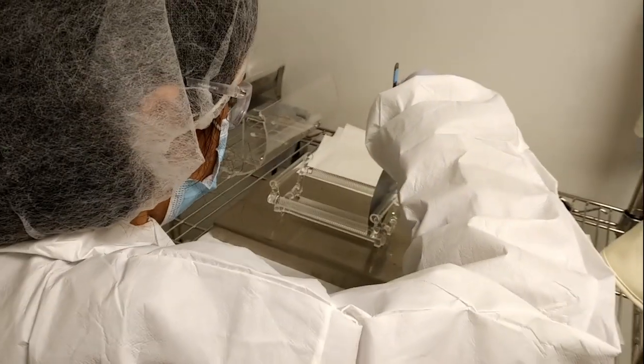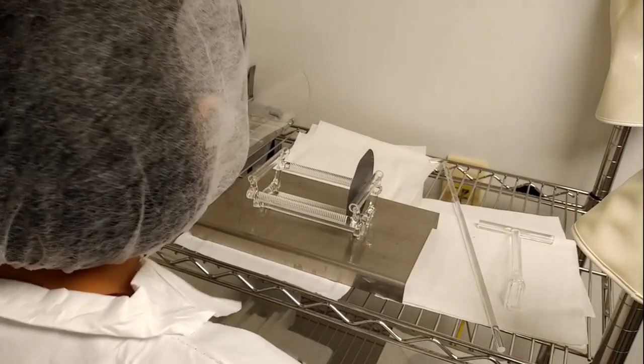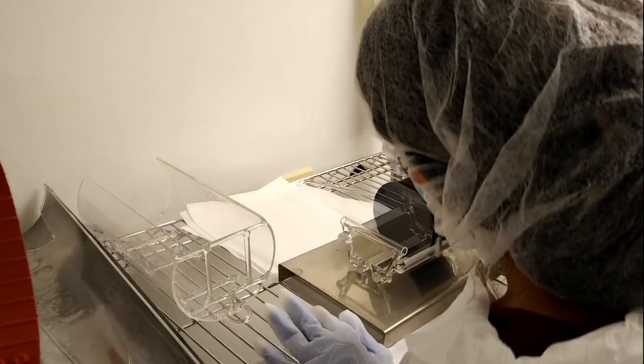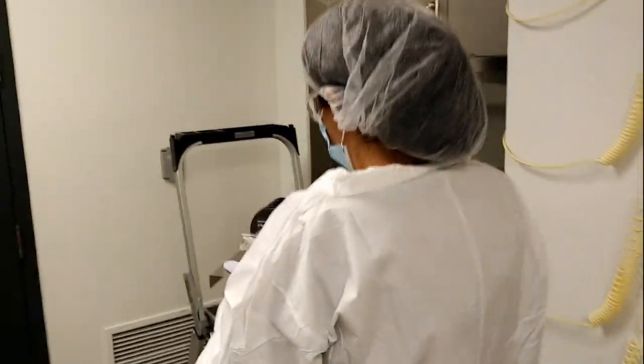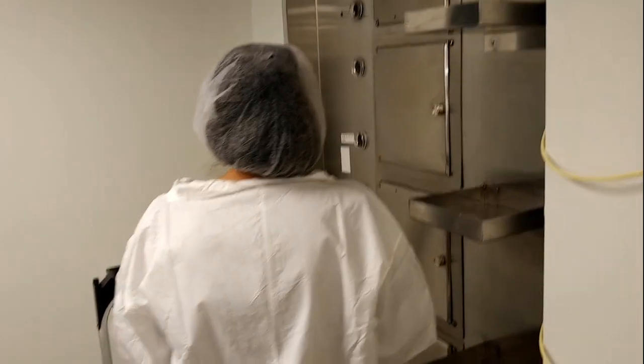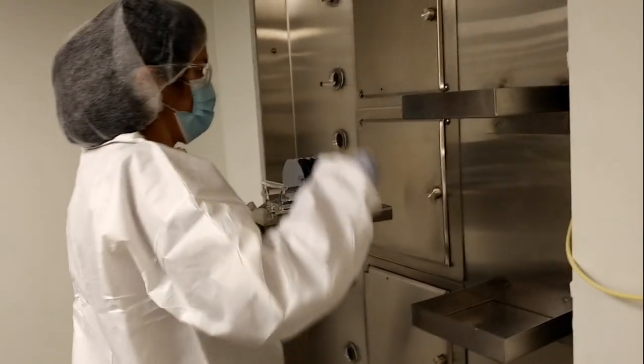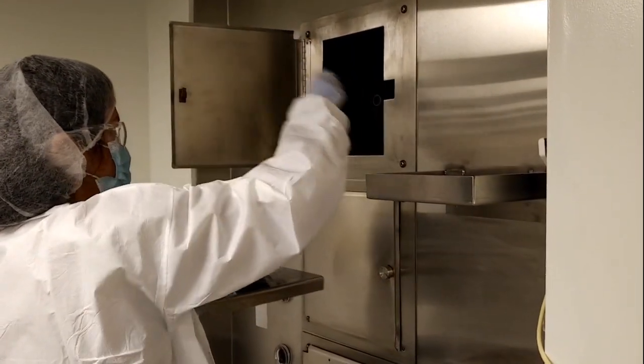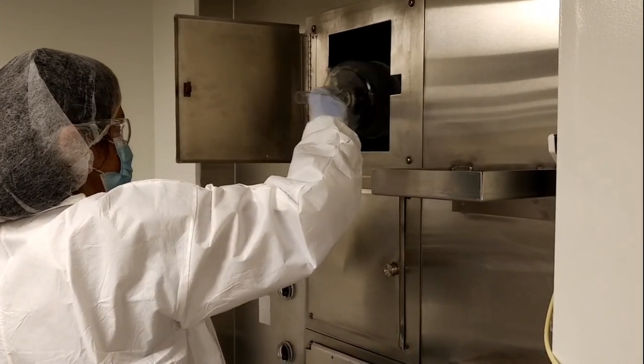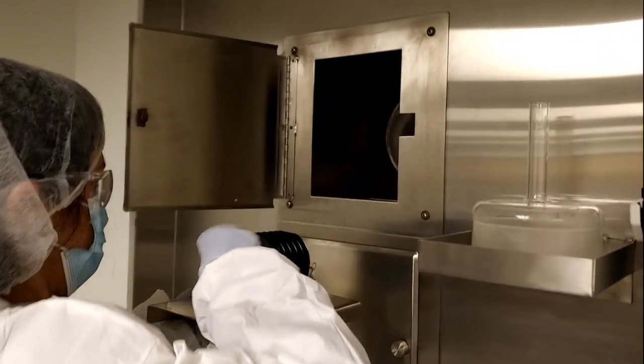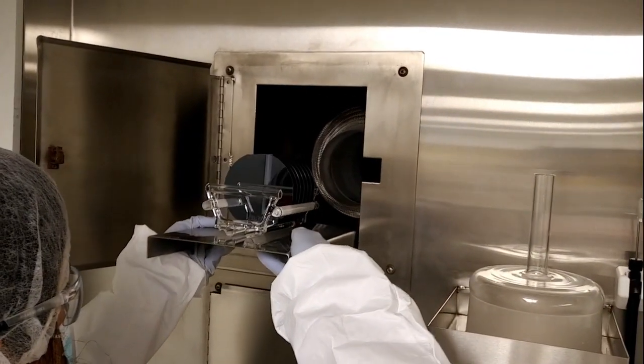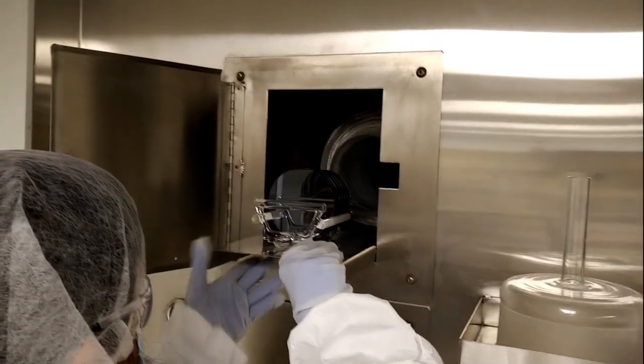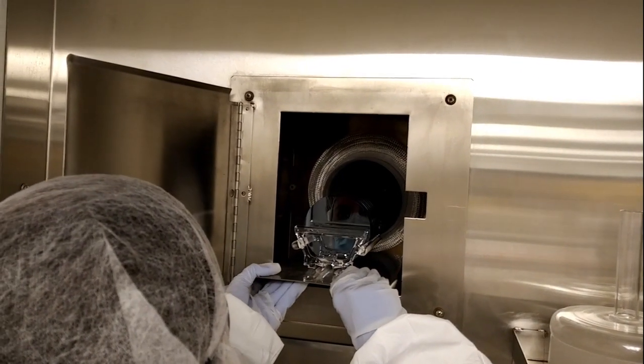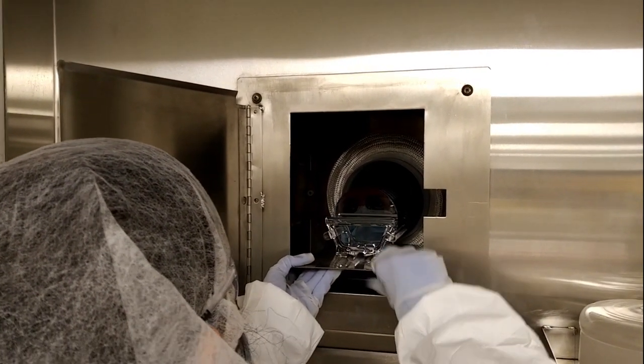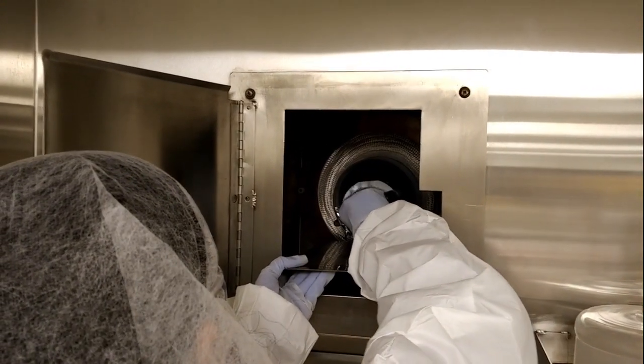A quartz boat is used to hold the wafers so they can be inserted into the furnace. The quartz boat is then moved into the tube furnace. Here, the wafers will be heated to 1050 degrees Celsius for 5 hours in an oxygen environment to facilitate dry oxide growth.